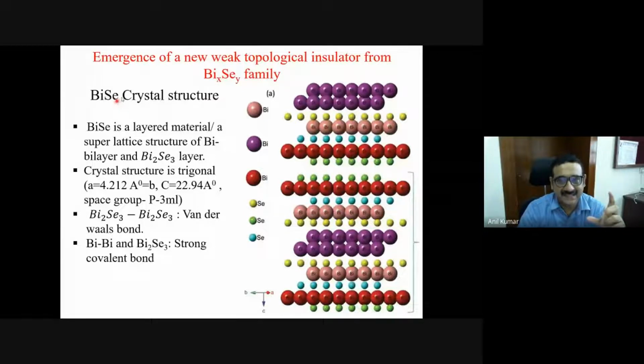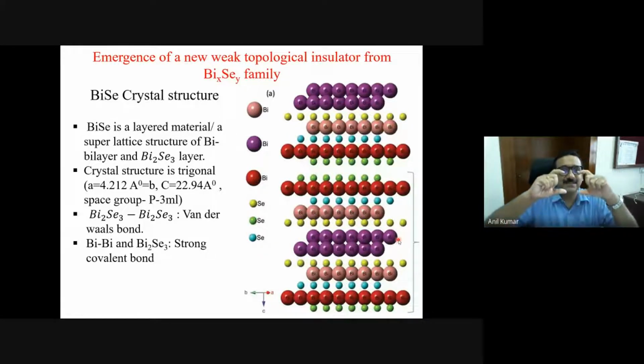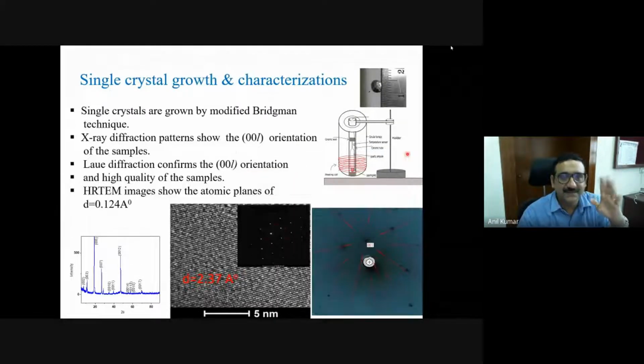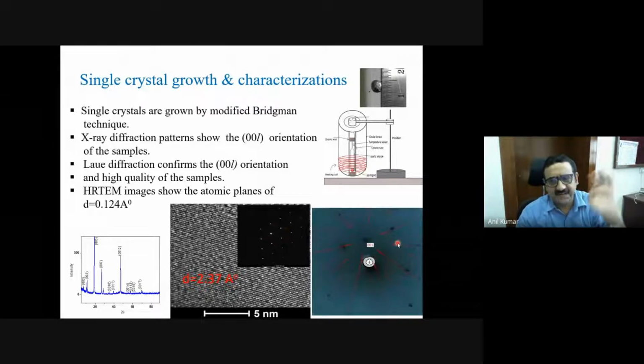So when we investigated the structure, we found that it has got a Bi2Se3 layer and another Bi2Se3 layer, and they are separated by a bismuth bilayer. So it is Bi2Se3, Bi2Se3, and a bismuth bilayer in between. And because of that, this is a BiSe structure, and this also can be exfoliated. So again, the crystal growth, and we find that all 00L orientations are available. We do high resolution TEM, and then we do Laue diffraction just to establish all the crystals which we make. We will establish that it is a single crystal by different kinds of techniques.